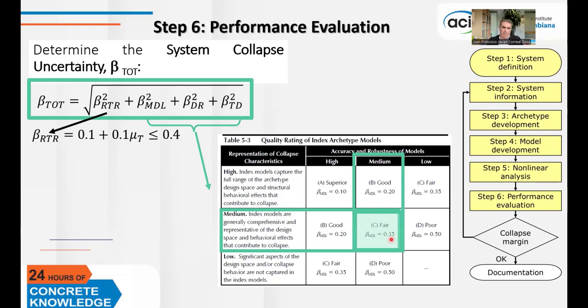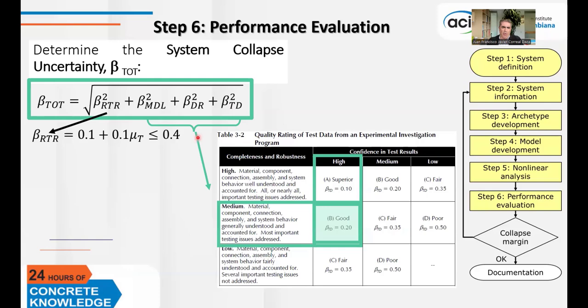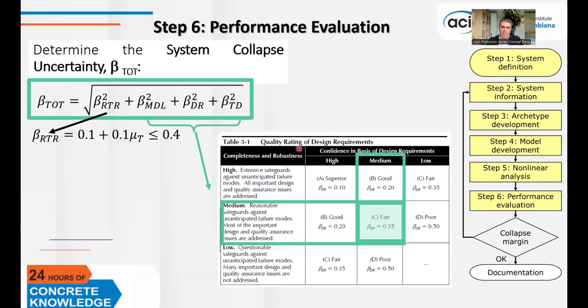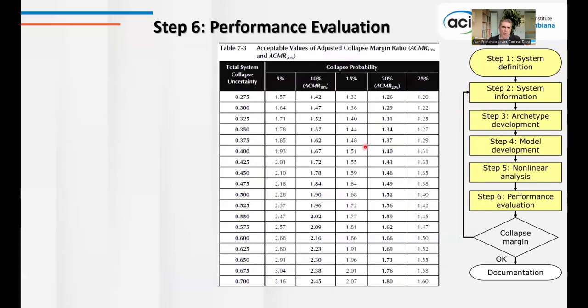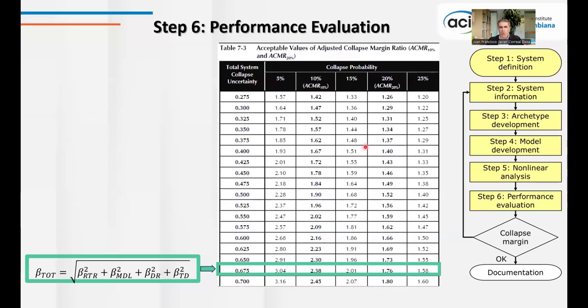close to 0.35. Then we do the same procedure, but now with Table 3.2, which is the uncertainty related to the experimental investigation. In that case, we have high for the confidence of the test and medium for the completeness, so it gives us a beta of 0.20. And the same we did with the design requirements, where we have a beta of 0.35 based on the qualification of confidence and completeness of the design requirements. Once we have the betas, we can get the beta total, go to Table 7-3, and compute the acceptable values of the adjusted collapse margin ratio for a collapse probability of 10% and 20%. The 20% value is going to be used to compare with the margin ratio that we calculate for every archetype.